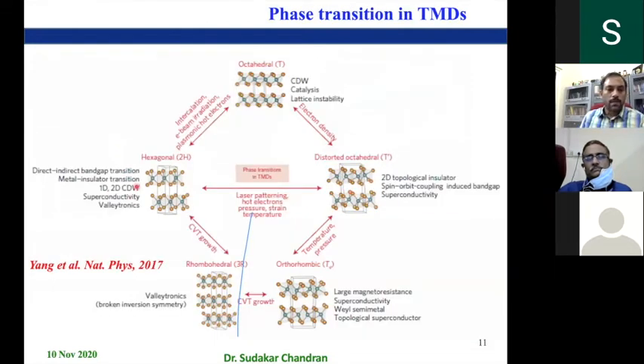For example, the different phase transitions that are known in the transition metal dichalcogenides are listed here. You can convert the hexagonal 2H phase to the octahedral 1T phase. Many times when you grow the crystals, 2H and 3R are the ones that coexist together, and it's also very difficult to differentiate them. The 1T phase can get to a distorted octahedral form. And of course, at very high pressures, one can get the orthorhombic structure. Each of these different phases has interesting properties.